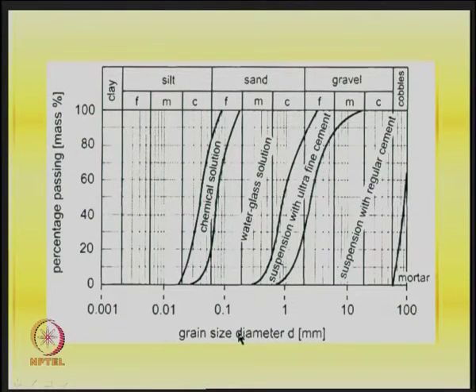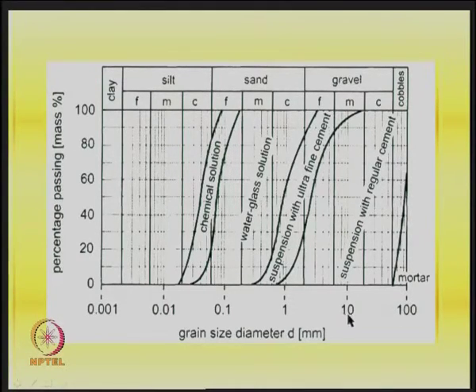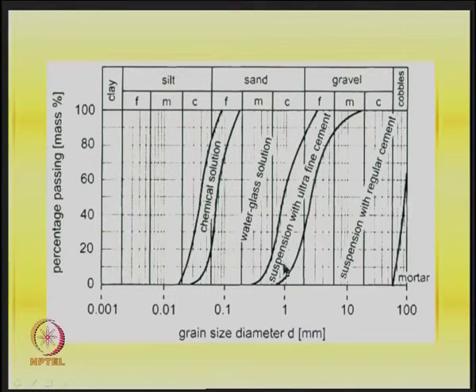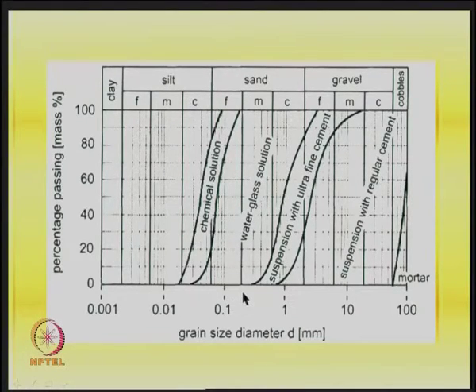For example, if the size is too coarse, mortar is sufficient. For a finer size — say 10 mm — a suspension with regular cement is suitable. For even finer material, a suspension with ultra-fine cement is used; then water glass solution; and for very fine materials like clays, you need to go for chemical solutions.